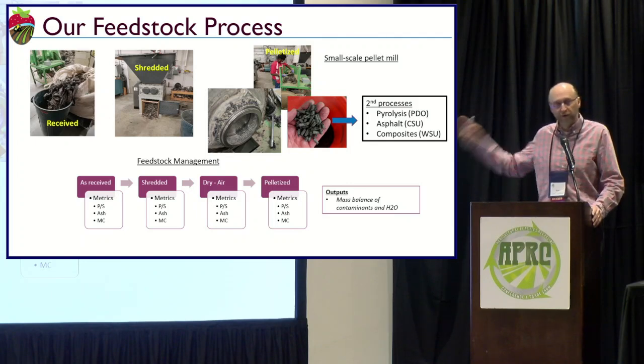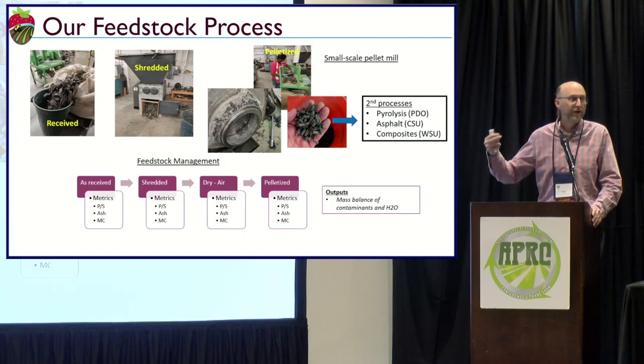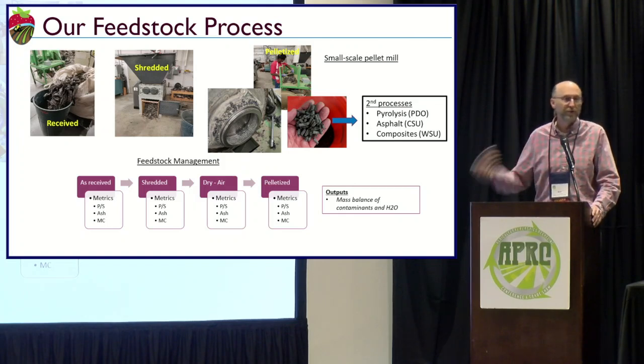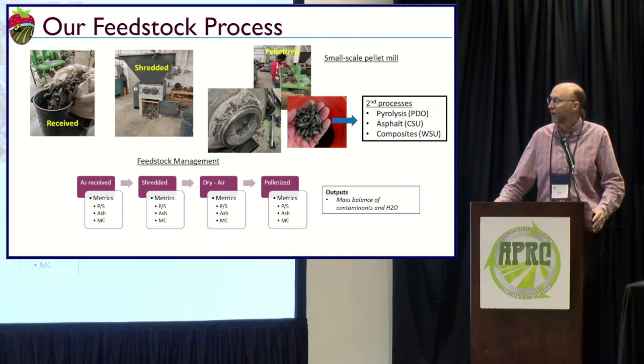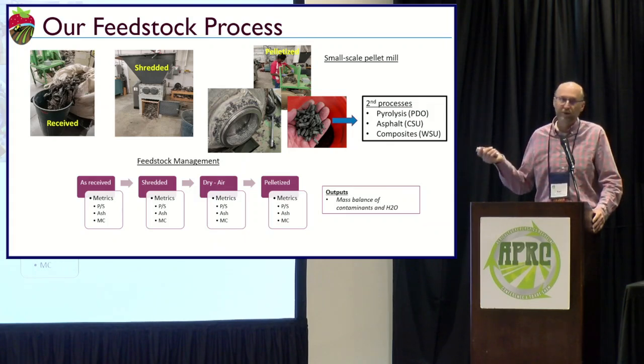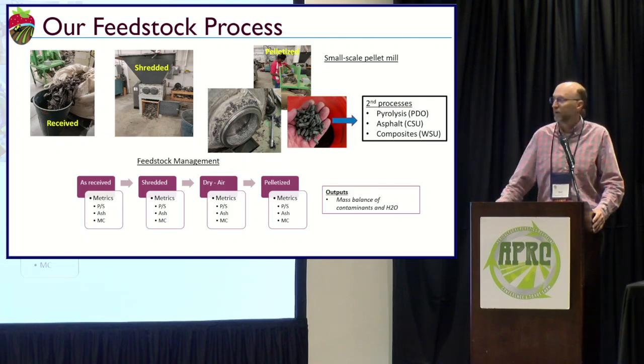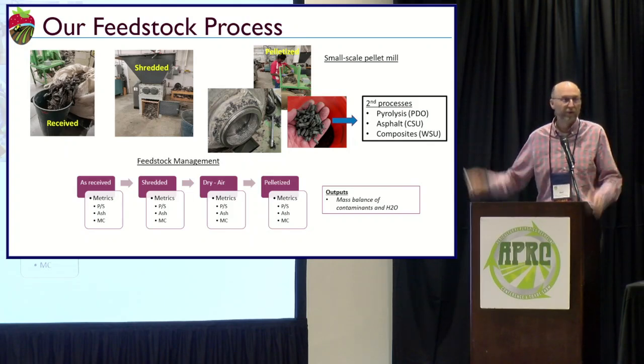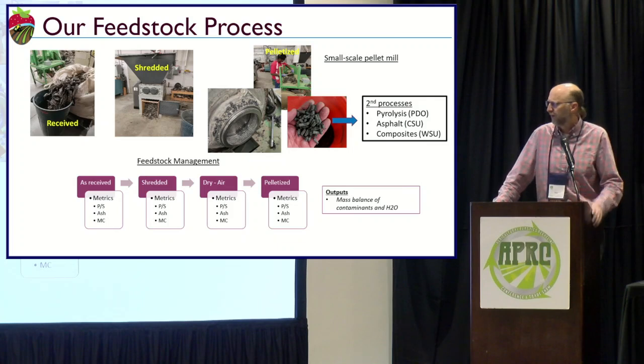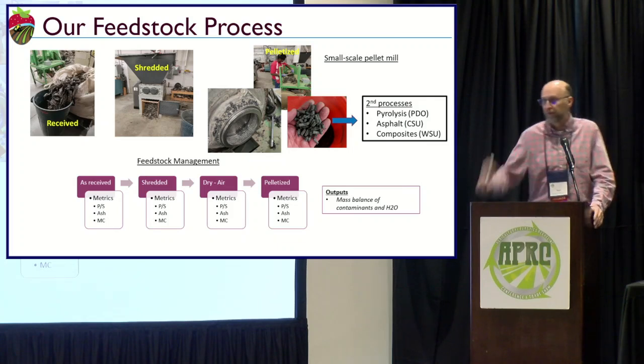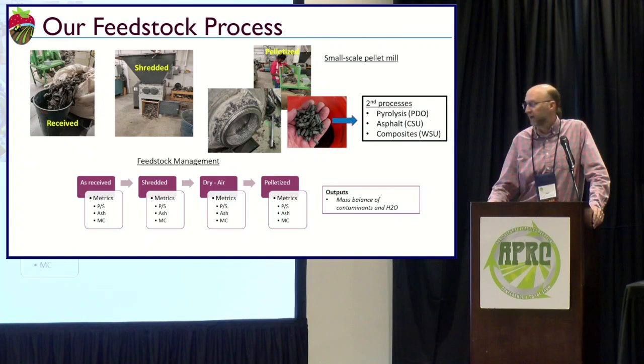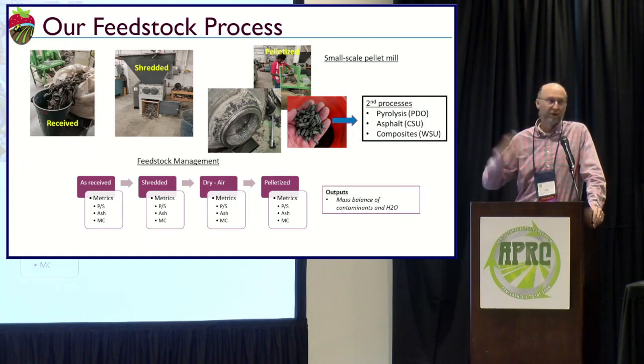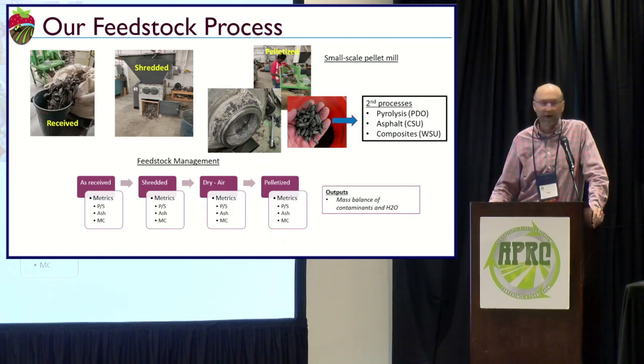Now, as we go through all that, we want to start taking a look at what's the quality, what's the moisture content, what's the soil level, the ash content, those kind of things. As we go through this feedstock preparation process, we want to see what we're doing to the plastic as we manipulate it and turn it into something that's useful. As you can see right down there, the PS is just the polymer to soil content ratio. I'll just look at just the soil content, or tramp load if you want to use Kevin's terminology. And then the ash content, where you actually burn all the plastic off and you look at the residuals from there, gives you more of a true sense of the inorganics that are in there.